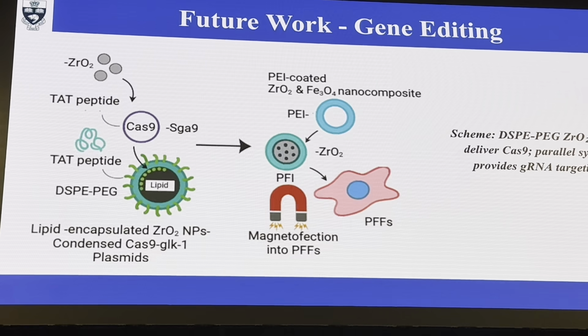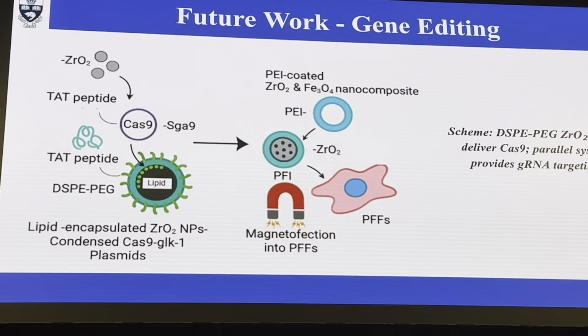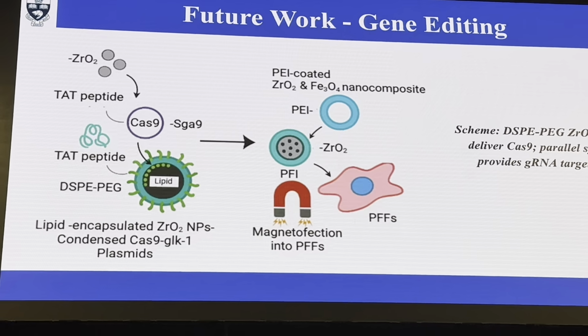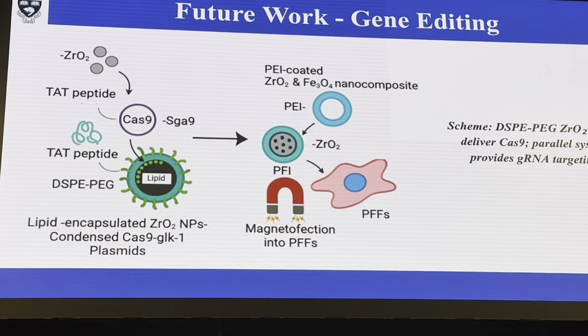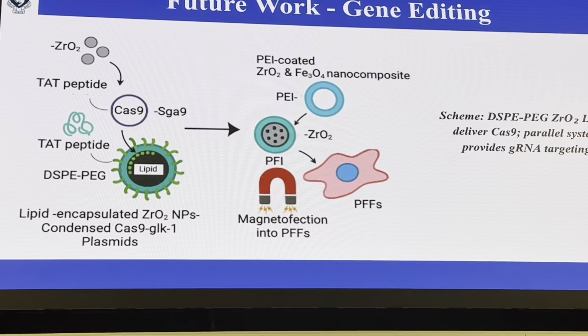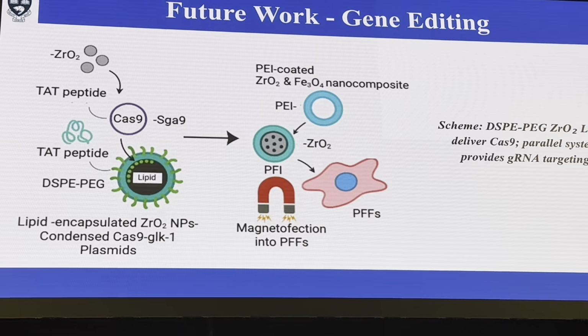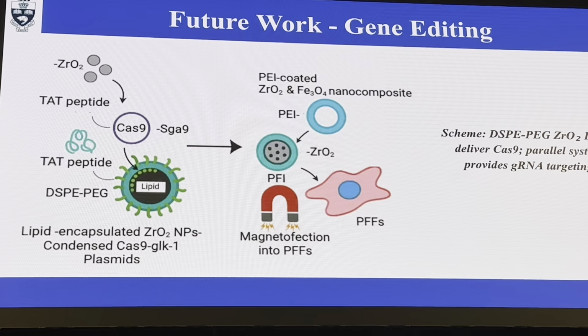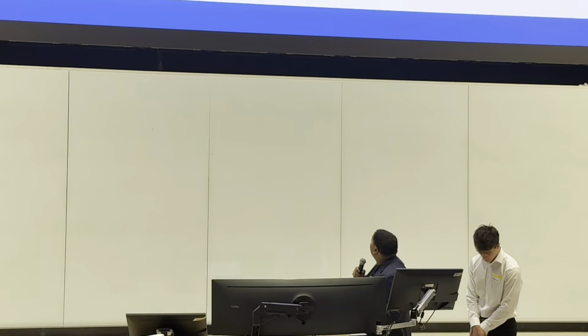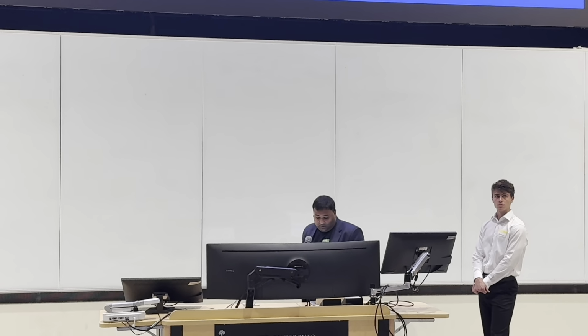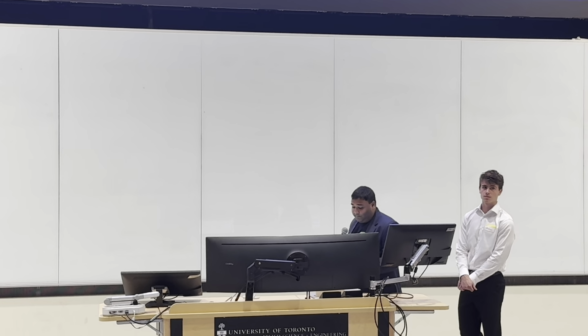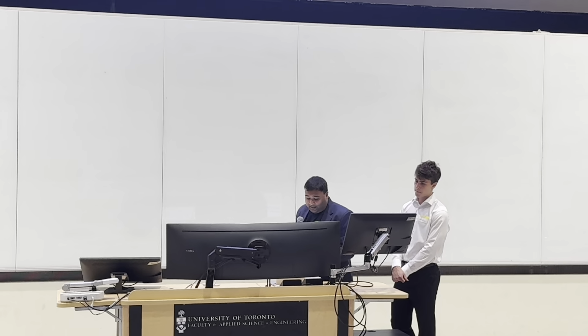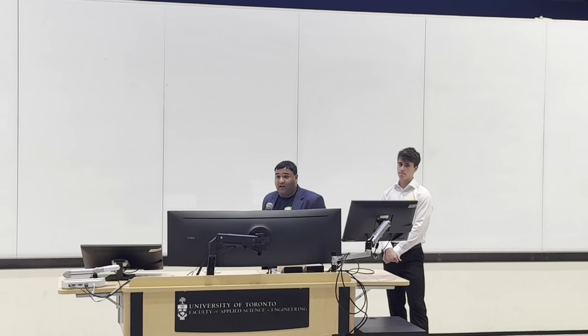This entire complex is then encapsulated in a DSPE layer that produces stable lipid nanoparticles suitable for biological delivery. To improve transfection, we have also provided doping of a coated layer with PEI-coated zirconium dioxide with Fe3O4 that is ferromagnetic and has a PEI layer. The magnetization helps in targeting the CRISPR-Cas9 to direct the particles into the PFFs, or porcine fetal fibroblasts. This system was specifically designed to deliver the Cas9 protein. In parallel, a secondary delivery system is used to guide the gRNA, which directs the Cas9 to the desired DNA target site for payloads.